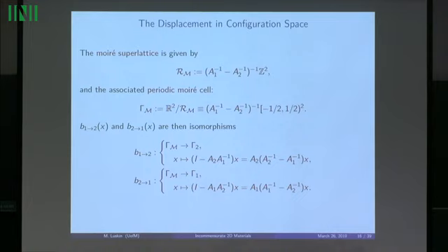So what this is saying is we actually have a very concrete continuum model for disregistry, and this really tells us what the Moire cell and the Moire superlattice are, because the Moire cell is simply the cell at which gamma 1 and gamma 2 are repeating. Remember, when gamma 1 and gamma 2 are the same, you're seeing the same picture.